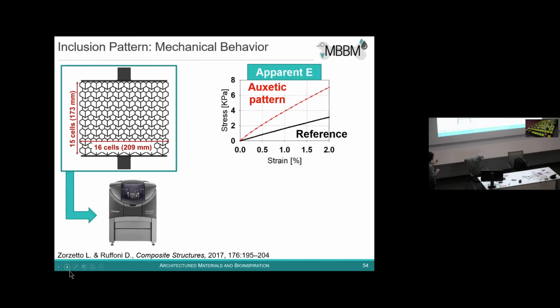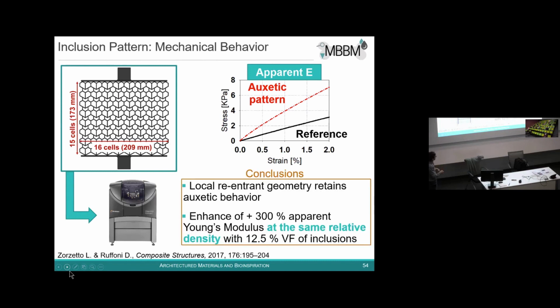So we did both simulation and experiments, and we see that indeed the apparent stiffness, so in the stress strain curve and the tangent modulus here, which tell us the apparent stiffness, is indeed higher for the lattice with the pattern of auxetic inclusion. And this is up to 300% increase in stiffness without changing the relative density.